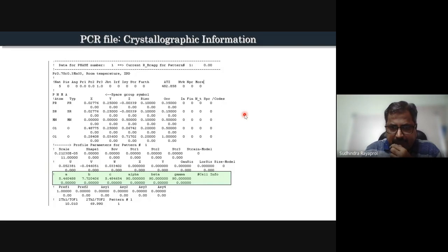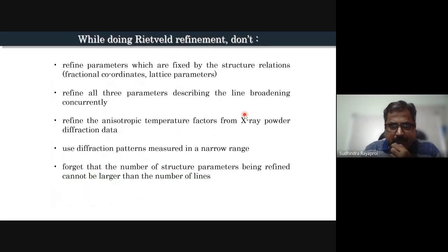Right. So if I continue now, next is what you should do and should not be doing. When you have fixed parameters, like fractional coordinates, say 0 0 z, 0 0 1/4 or 0 0 0, you don't refine those parameters. The lattice parameters are constrained by the crystallographic lattice systems. So there are certain conditions, like in a cubic, all sides are the same. In tetragonal, 2 sides are the same and 1 is not. Those conditions you have to keep in mind when you are defining.